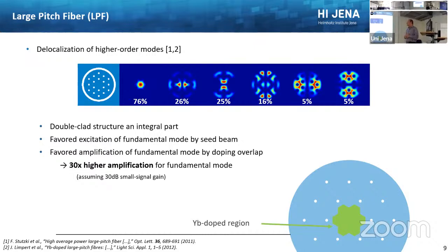On the right side, you can basically calculate the modes that the fiber guides. And here you can see the following point. If you start with a Gaussian beam at the input of your fiber, the chance is a lot higher that you will excite one of the modes on the left side, also the fundamental mode of the fiber, and not these higher order modes, because they are quite outside of the central region. So this is already a favored excitation.